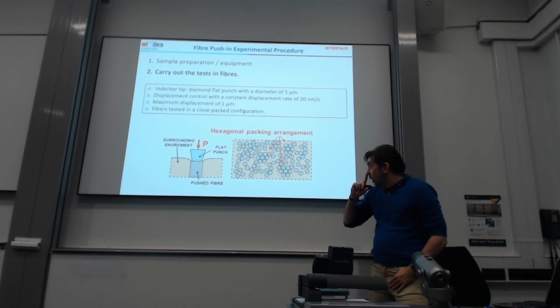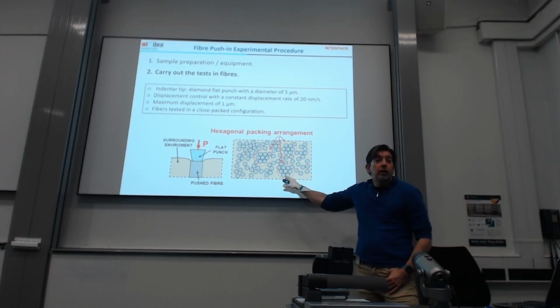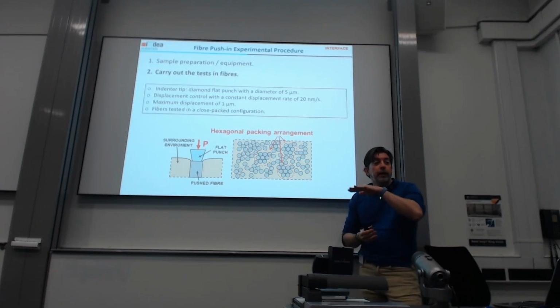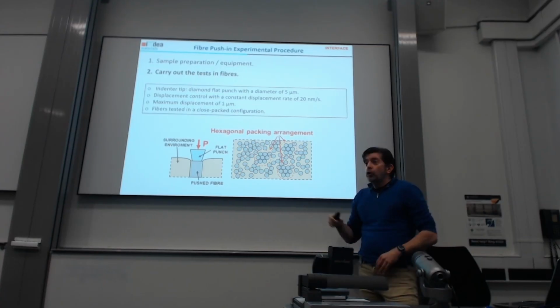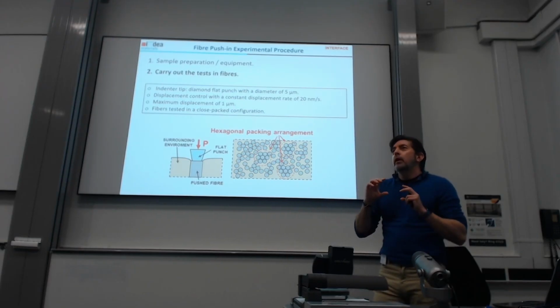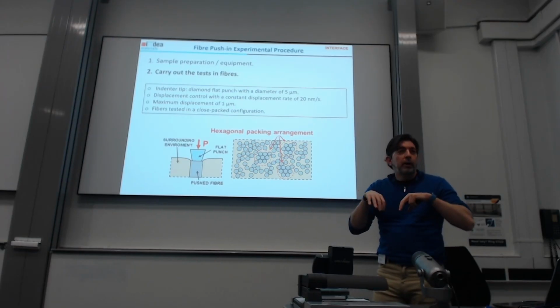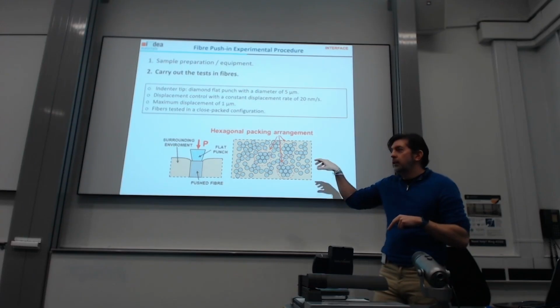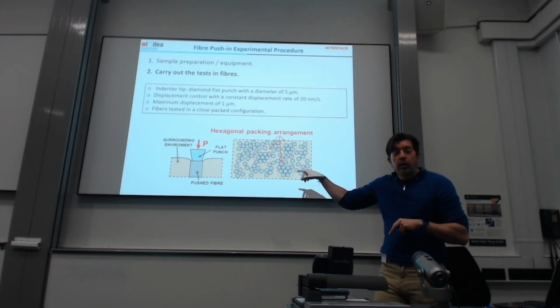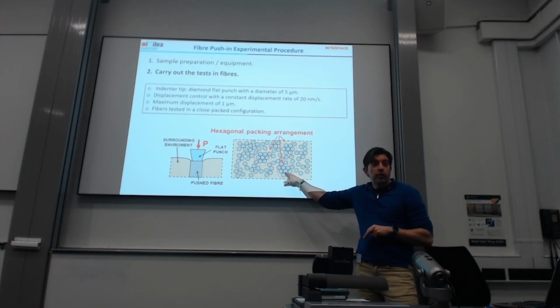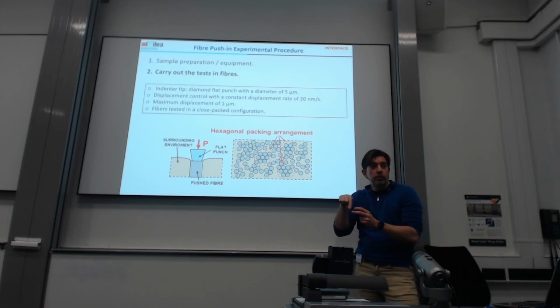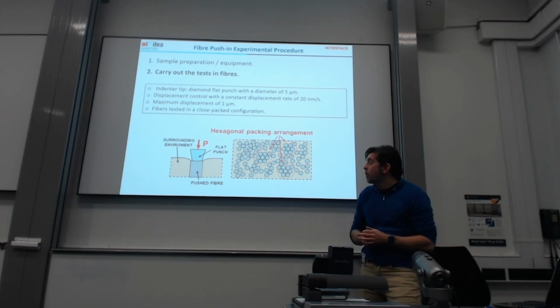And we are going to test fibers which are in this hexagonal close-packed configuration, like the top face of a hexagonal close-packed unit cell. Because we need to do this where we have a constant surrounding environment. We're not just going to test any fiber randomly. You look for this kind of fibers inside this hexagon. It's like a honeycomb structure.